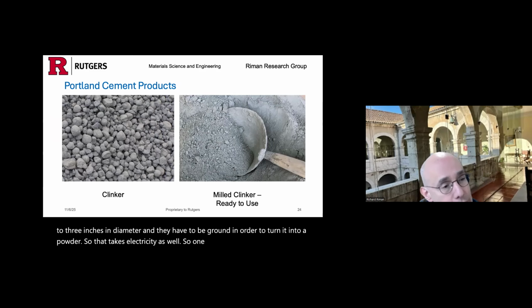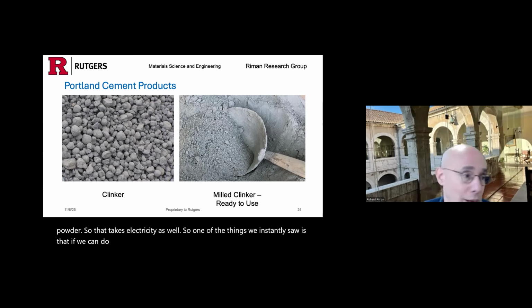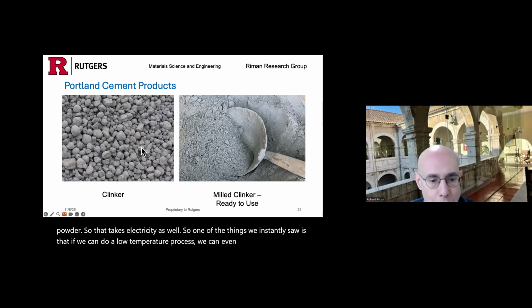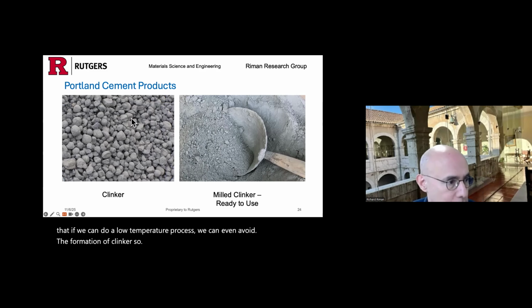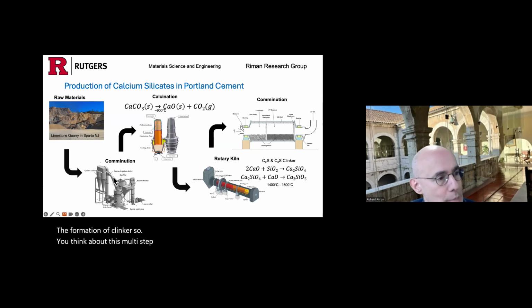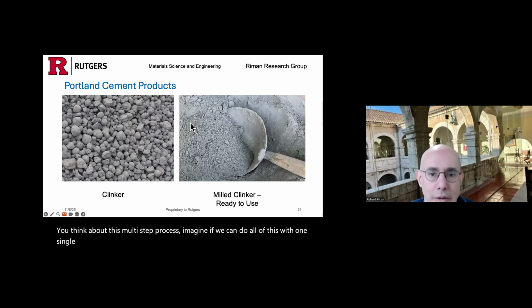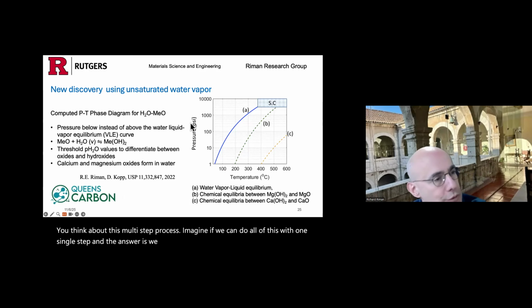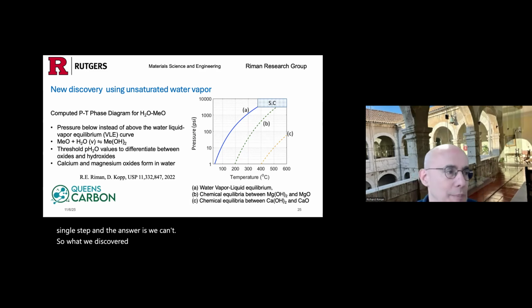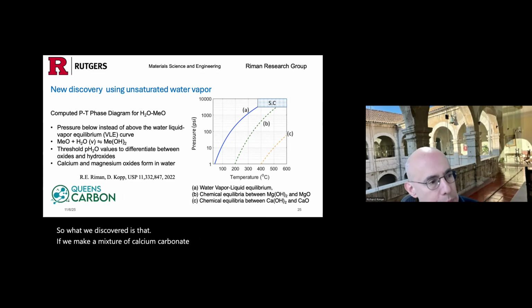So one of the things we instantly saw is that if we can do a low temperature process, we can even avoid the formation of clinker. So you think about this multi-step process. Imagine if we can do all of this with one single step. And the answer is we can. So what we discovered is that if we make a mixture of calcium carbonate and silica, and we expose it to water vapor under pressure, we can make cement directly from our reaction vessel.